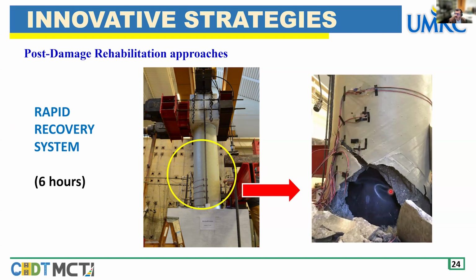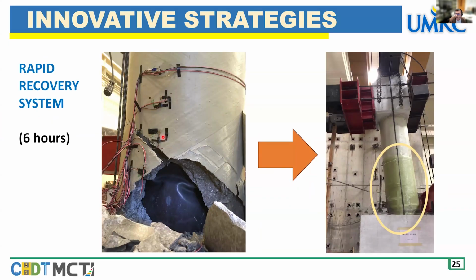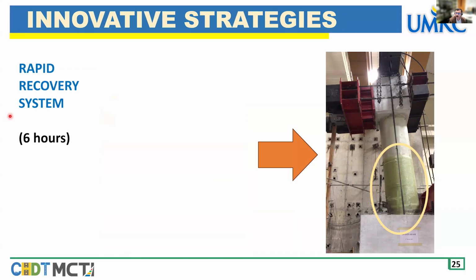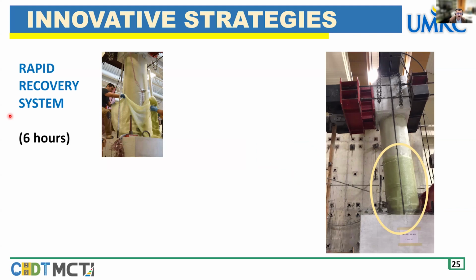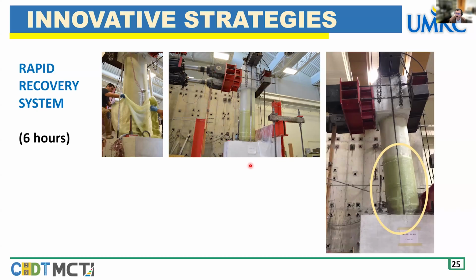This is the damage, as we can see here, severe damage, especially in the FRP, and a huge loss in the confined concrete, which is in the interface between the FRP and the steel tube. So what's the proposed rapid recovery system? From this shape with the huge damage to a column ready to be tested again under the same loading conditions. First, we started with wet lab fabric FRP, using high strength glass fiber fabric saturated with epoxy resin. We took this as a blanket and wrapped the column in this region, after cleaning and removing all the loose concrete. As you can see, we just tied the FRP from the top and left it to settle for an hour.